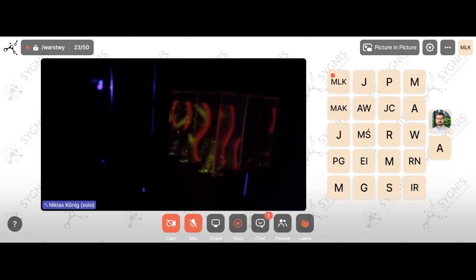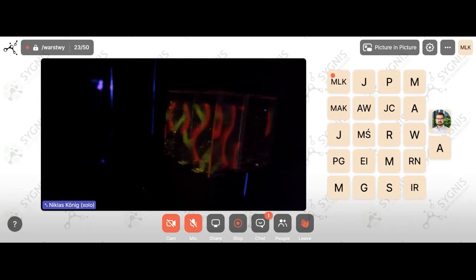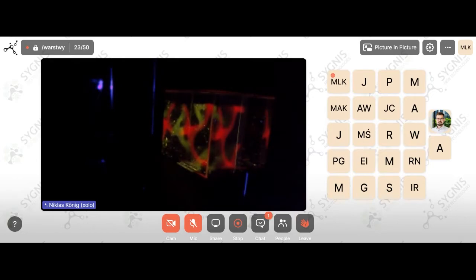And yeah, I mean, we have some flexibility on the material side. We don't know what you expect there, but in the end, it is very wide. In the end, we found that we can basically polymerize any acrylate. Usually we take methacrylates to have less shrinkage, but for example, GelMA, acrylamides on a protein, and we can also polymerize pre-ceramic polymers that contain these acrylic groups to allow for access to ceramics after a sintering process.